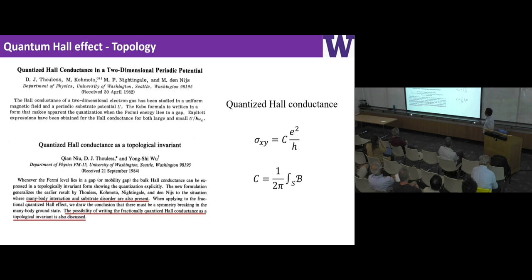And later, a couple of years later, Niu, Thouless, Wu and collaborators came up with another quite exciting paper. They extended the previous TKNN paper into the regime with many-body interactions and also with substrate disorder. In this paper, they were able to show that the fractional Chern number is also a topological invariant. At the time they did this calculation, there was no dependence on magnetic field, although I don't think they realized the fractional quantum anomalous Hall effect.